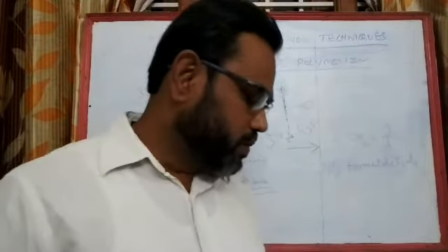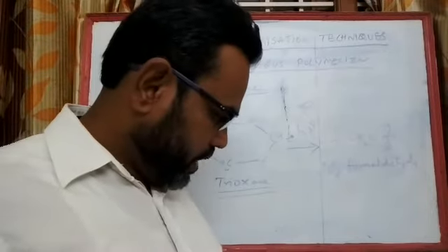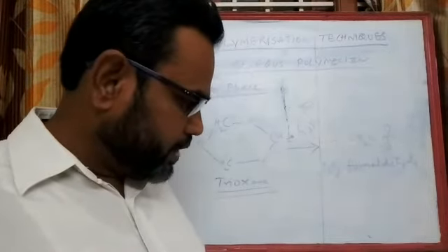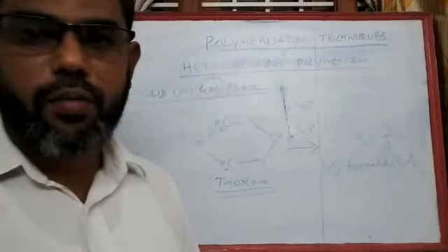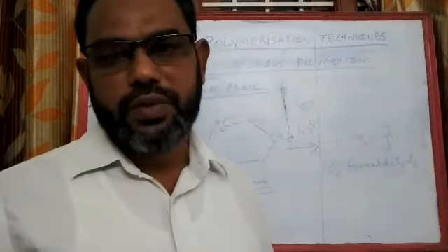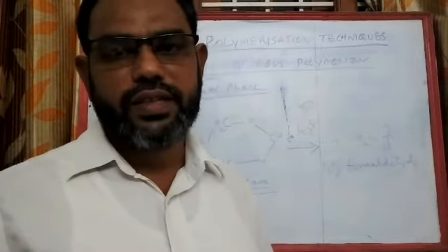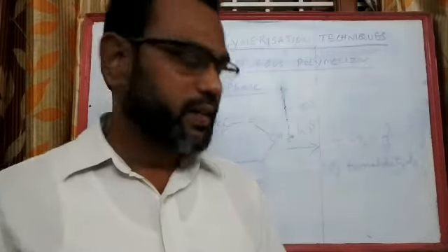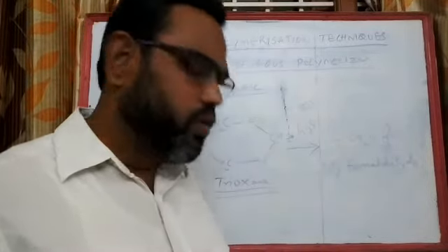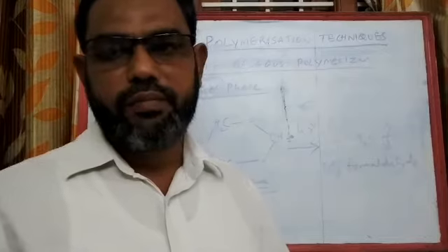Similarly, you can also prepare polypropylene polymers. The gas pressure should be maintained at about 4 to 5 atmospheres, and the column should be filled with the catalyst in a fluidized bed form.